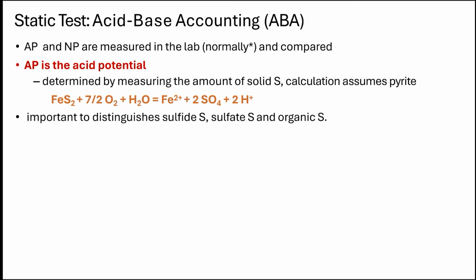So AP is the acid potential, and that's normally determined by measuring the amount of solid sulfur. And the calculation assumes it's pyrite, and it makes surprisingly little difference, even if it is not pyrite. But what is important is to do an analysis that distinguishes sulfide sulfur, which will tend to oxidize, as shown. This is slightly different from the equation I showed before. Sulfate sulfur, which is already oxidized, like if you had gypsum or barium sulfates or something else in your rock, that's not going to contribute to acid potential, so you don't want to count it. And organic sulfur, which is generally considered not to contribute, but sometimes it's ambiguous.